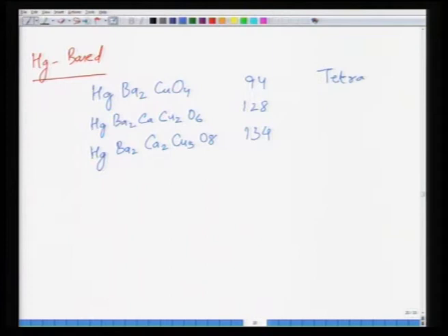So, you can see that these cuprates, which have layers of copper oxides, if you tune the composition by putting in a variety of atoms in the structure, you can change the TC quite well. The problem with mercury and thallium based is that they are difficult to handle. They are poisonous, and many countries have banned or restricted their use. So, as a result, they did not pick up too much, but still a huge amount of research was done on yttrium